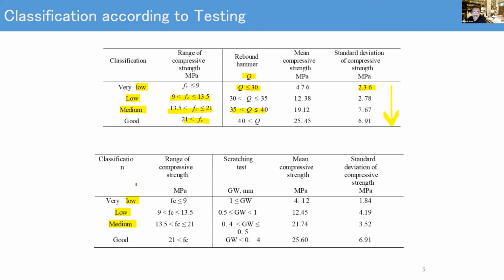And if we go for the classification for compressive strength, if we look at it based on the scratch width, we can see if groove width is greater than 1 millimeter, then it can be 9 MPa and less. But if the groove width is 0.5 to 1 millimeter, then it is a second range, and then a third range and fourth range. So there is a good correlation between the two methods. First method is based on the Q value, and the second one is based on the groove width.